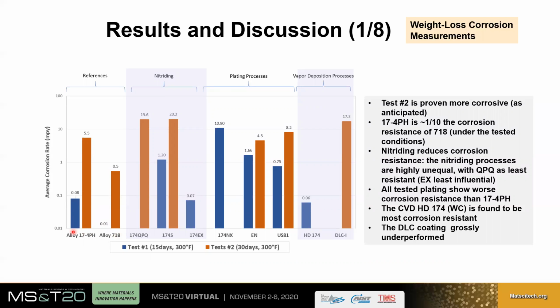The same observation we made also for test number 1 in blue here, where this number of 0.08 has to be compared to 0.01. So essentially, the takeaway is that 17-4 PH corrodes approximately 10 times more than 718 in the conditions selected for this study. So with this in mind, now let's look at the nitriding first.